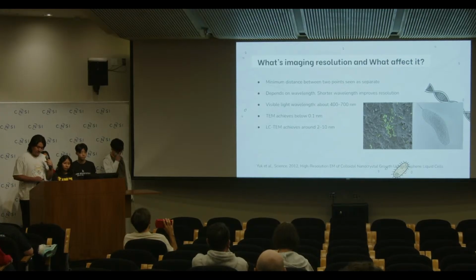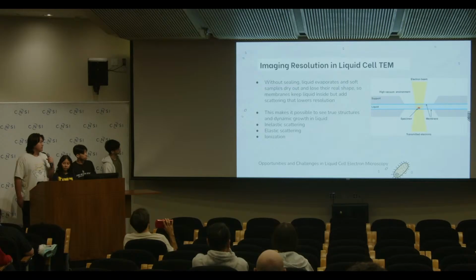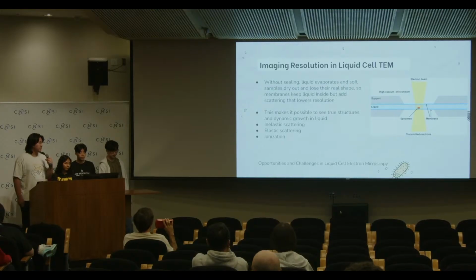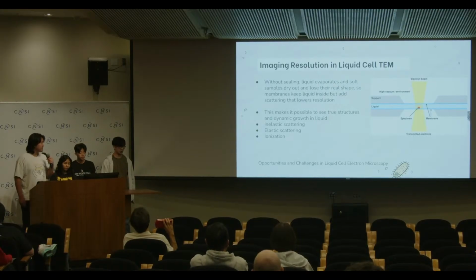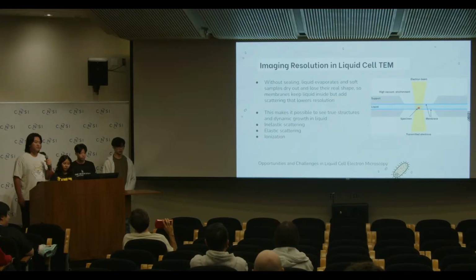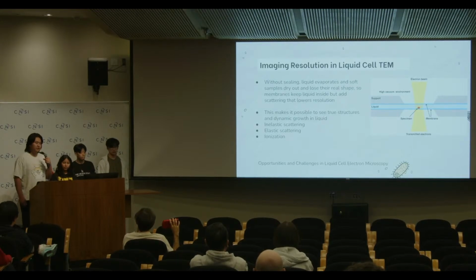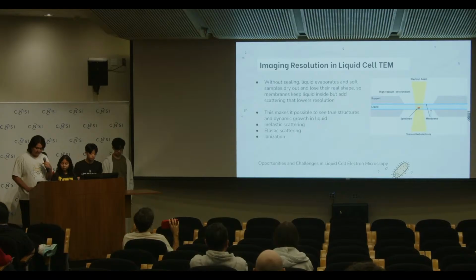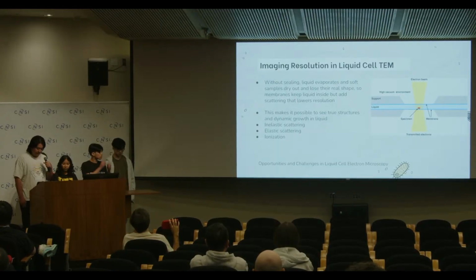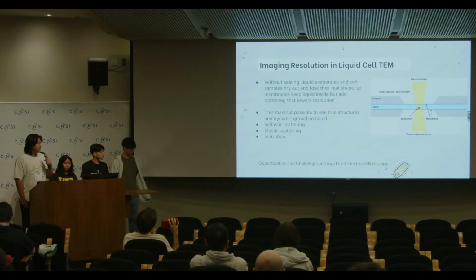And I will show you why it decreases the image resolution. We can see from the images that there are two membranes and the liquid layer. When the electron beam gun shoots the electron beam through the layer, it will deflect and scatter. Since we know that the microscope needs to focus, the scattering will separate the channel and decrease the resolution. And there are actually four types of scattering,